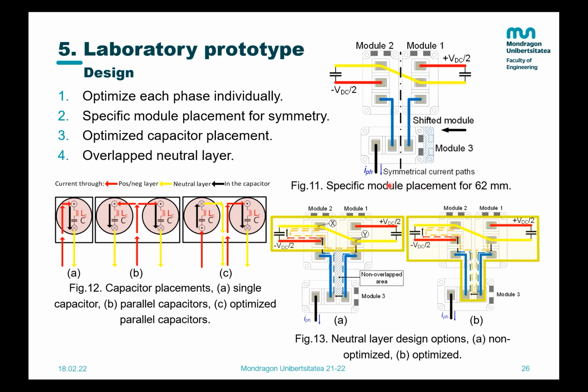We used optimized capacitor placement by connecting 2 capacitors in parallel and in opposite directions. So we were forcing opposite currents here, and we could take advantage of the magnetic cancellation concepts. And finally, we actively overlapped the neutral layer to the whole switching loop. As you see here, the neutral layer doesn't cover the whole switching loop, and there is a non-overlapped area here, whereas in the optimized neutral layer, the neutral layer overlaps the whole switching loop. So it allows opposite currents in the whole switching loop, taking advantage of the magnetic cancellation concepts.